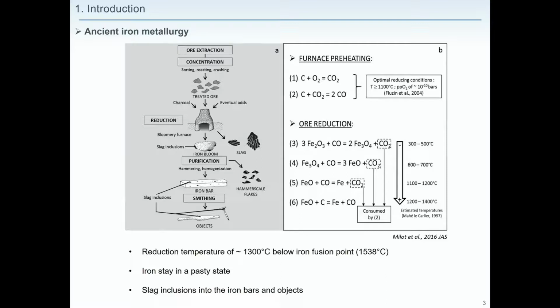I will not detail the corresponding reactions here, but the important point is that the reduction temperature of iron is about 1,300 degrees, which is below the fusion point of iron. So the iron bloom will stay in a pasty state, and some slag inclusions could be trapped in the iron bars and remain in the objects despite the purification step.